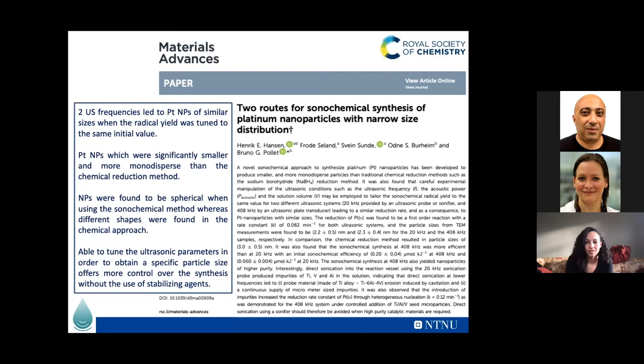The problem is that 10 years ago, people were using quite a lot of surfactant or alcohol. Surfactant, as we know, if you want to get rid of it on a nanoparticle, is pretty much a pain. You need to do a lot of chemical cleaning. But what we're trying to prove is that you can tune the radical formation in order to get a fixed range of nanoparticles with your platinum. And we got some very good particle sizes, around 2 to 2.5 nanometers in size.